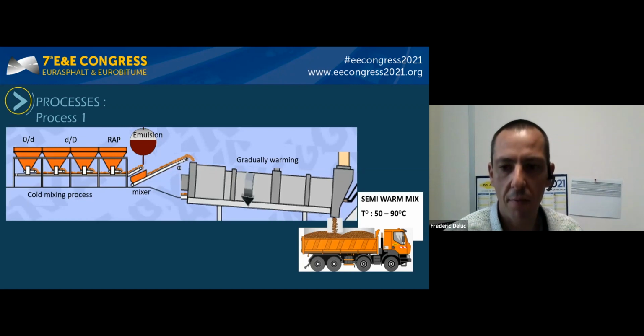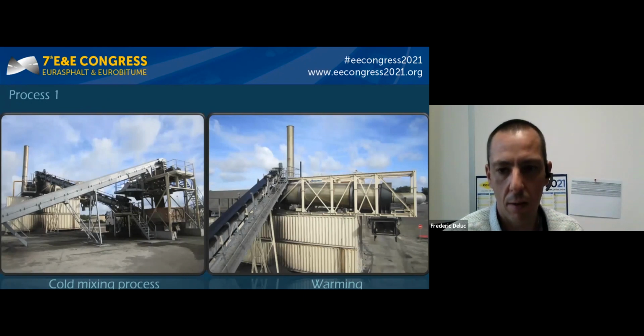There are currently two manufacturing processes, which I shall now describe. The first consists of manufacturing a cold emulsion mix from sand, aggregate, RAP, and emulsion. This mixture is then heated in a warming tube which produces the semi-warm mix by raising the temperature to between 50 and 90 degrees. The photo on the left of this slide shows the cold manufacturing process, and the photo on the right shows the warming of the emulsion mix in the tube.